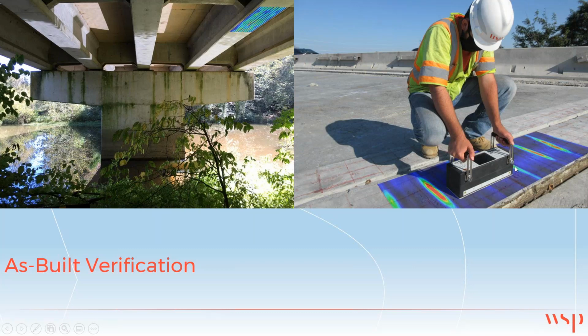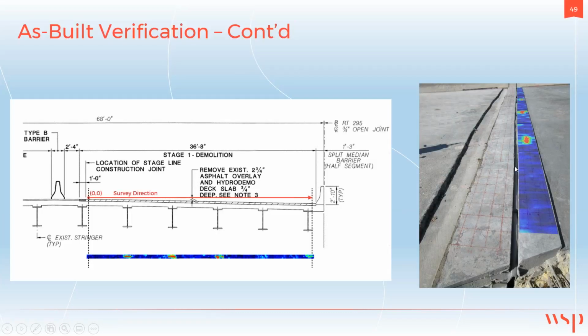We can have a closer look at the bridge header, but at a different cross section. These are the girders as we identified using NDE. The red ones are the girders. And when you compare this with the plans, you see that the girder locations were captured quite accurately.